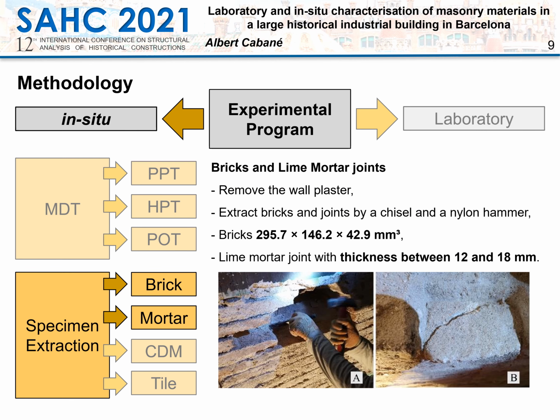The in situ program presents a second step based on the specimen extraction. To start the extraction of the masonry components, it is necessary to break a brick using mechanical tools. The extraction of the bricks and lime mortar joints was carried out manually by using a thin, sharp chisel and a nylon hammer. During the extraction, proper conservation and in situ classification of the samples is essential.